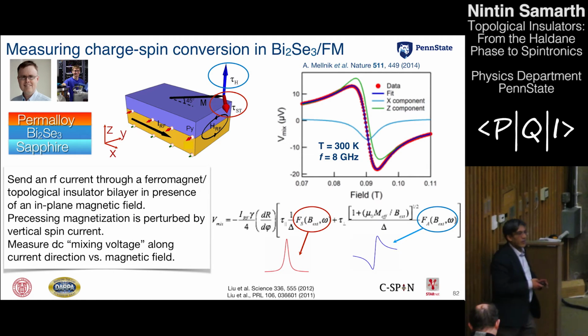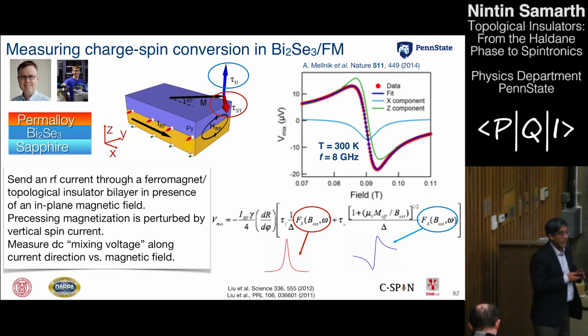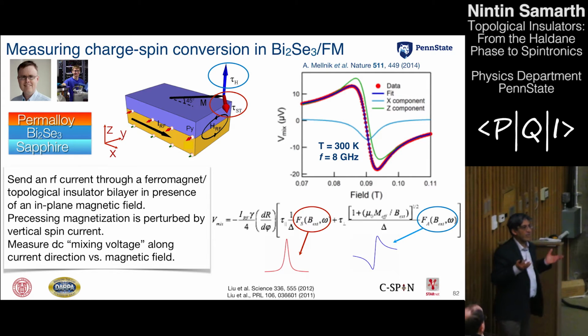So we undertook this experiment first in a collaboration with Dan Ralph at Cornell. It's an experiment that really went off in a direction that there were no real predictions over here. So in Dan Ralph's group, what we did was we made bilayers of permalloy, which is a ferromagnet, with bismuth selenide, which is the topological insulator. You then drive an RF current through this combination, through this bilayer. And you can monitor the precession of the ferromagnet.